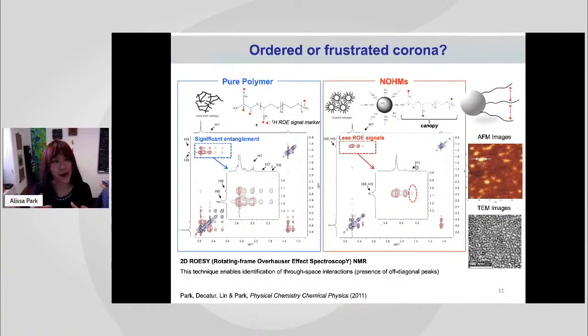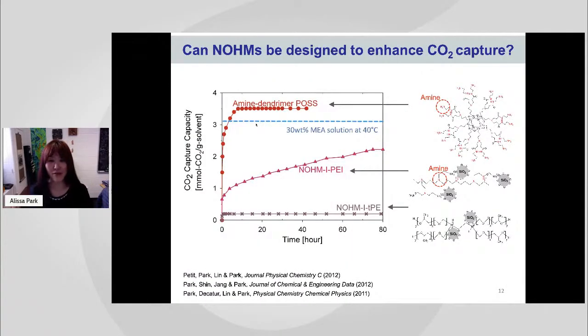After that, we wanted to see whether, by tethering these polymers, we really change the structure of these polymers, because that tells us whether there is any entropic effect during CO2 interaction or CO2 capture. This is 2D ROESY NMR data. On the left is the pure polymer, which is untethered. On the right-hand side is the NOHMs material we made with that same polymer. As you can see, there is a lot less signal in the 2D ROESY NMR, which means that polymers in NOHMs were stretched out from each other, so there was a lot more creation of free volume in between these polymer chains. Because of that, we were able to provide better accessibility along the polymer chains to the functional groups we wanted. So next, what we had to do was just add more amine along the polymer chain.